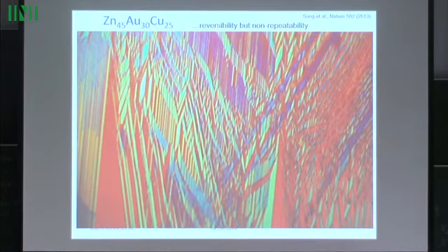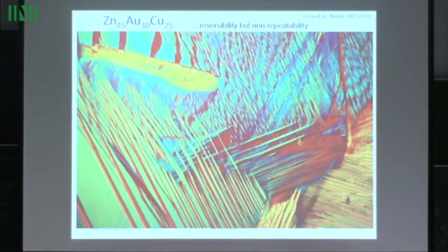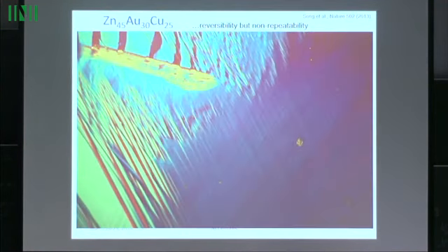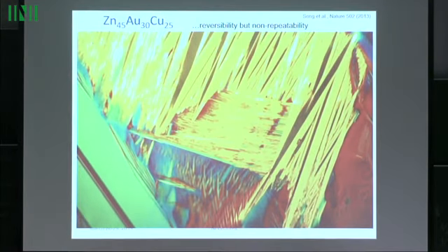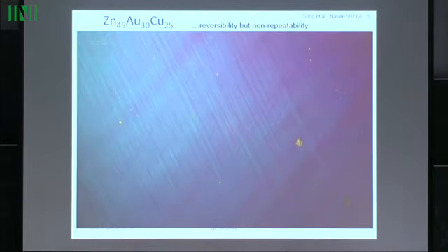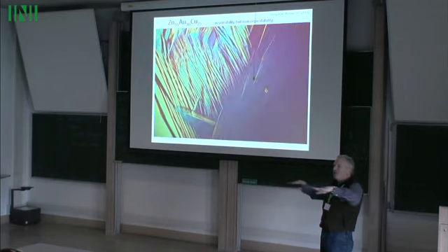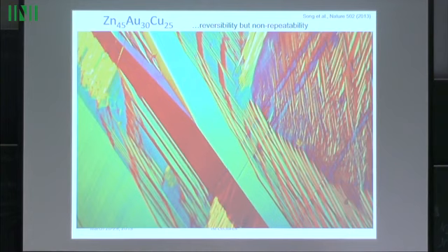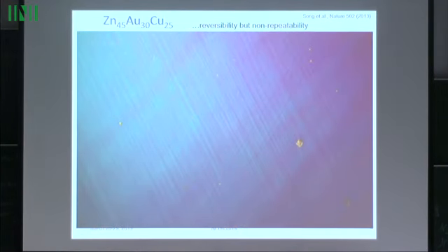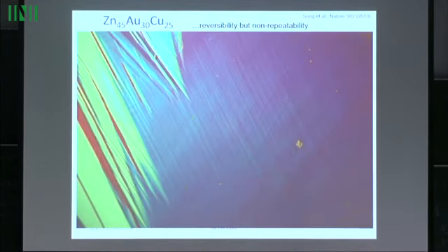So it seems that because of all these additional compatibility conditions, somehow the material really doesn't know how to get started, and each frame is different. But I don't have an explanation for this. You could argue the other way. If the energy landscape is so flat it doesn't know where to get started and it goes in any path, then why don't the defects in the material bias the material more than in an ordinary material? So it's completely unclear why you get these differences.